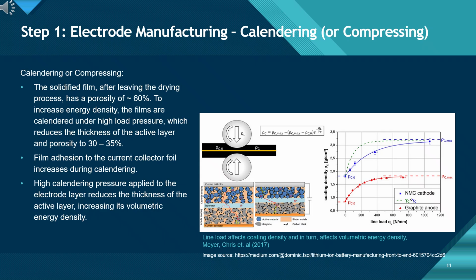Electrode manufacturing, calendaring. Once the electrode film leaves the dryer, it retains a high porosity of approximately 60%. To improve energy density, the electrodes are compressed in a process called calendaring. In calendaring, the electrode passes between two heavy rollers under high line load pressure. This reduces the thickness of the active layer and lowers porosity to approximately 30 to 35%. The result is a denser electrode that can store more energy per unit volume.